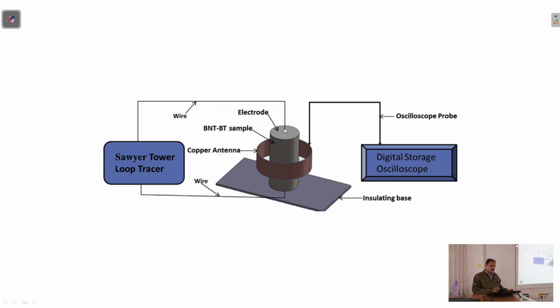And connected the wires, and then this is the power source, and using the power source we gave the alternating current input. So for those who are a bit familiar, if you want to have some output from a piezoelectric material, then the input has to keep varying. Here it is electrical input, but let me give the example of force input only. Suppose you apply force, you keep it at that, then your signal or voltage, whatever you are getting, will actually get lost after some time.